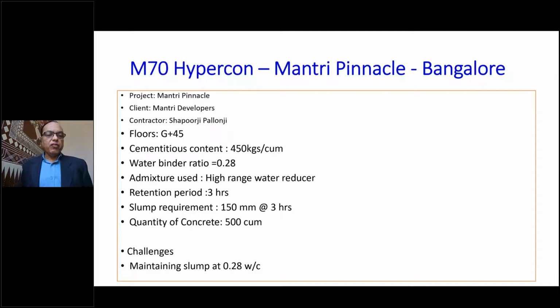It had 45 floors, ground plus 45 was the structure, and the cementitious content was 450 kg per meter cube. The water binder ratio was 0.28, and high range water reducers were used, of course. And the slump requirement was 150 millimeters. That is the slump required at 3 hours, not at 1 hour or not at 10 minutes. Even after 3 hours of concrete mixing, the slump should be a minimum of 150, so that you should be able to pump.